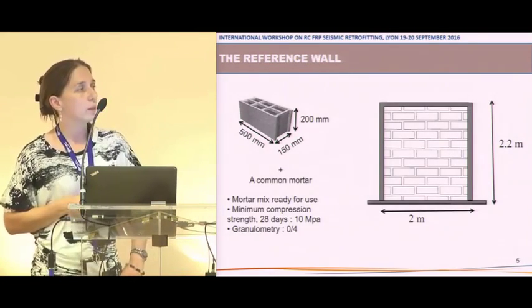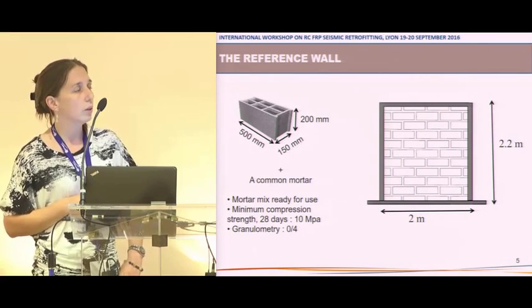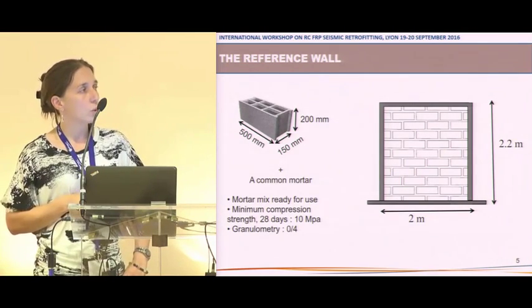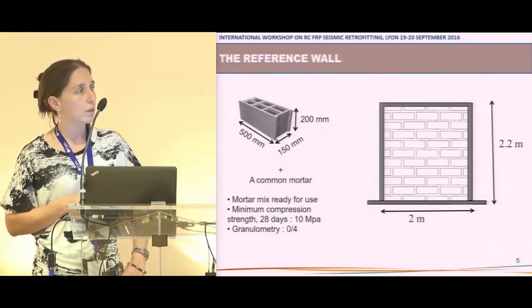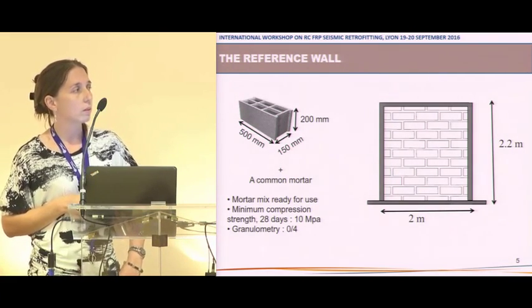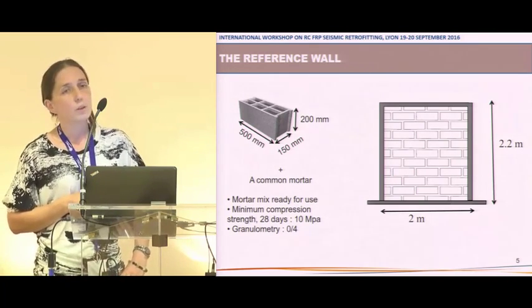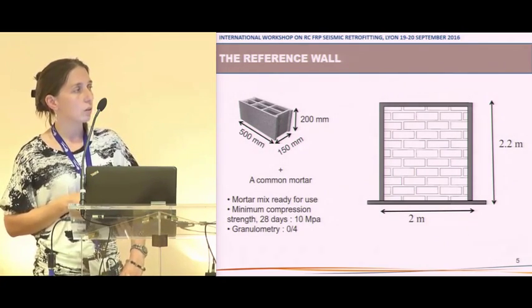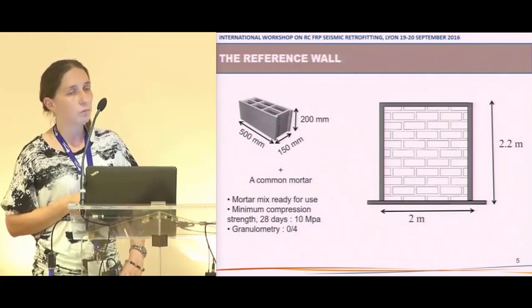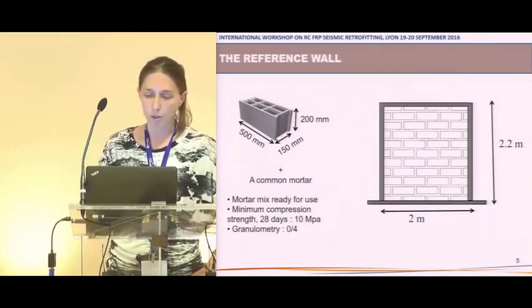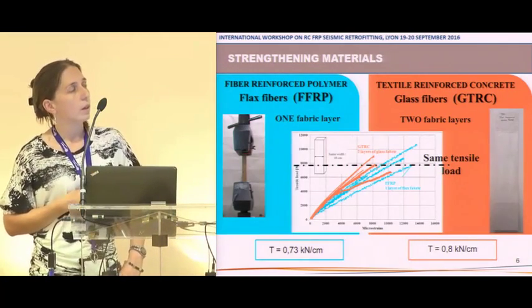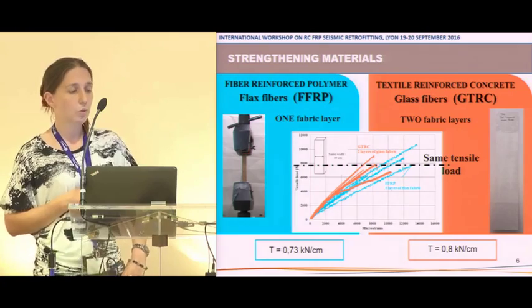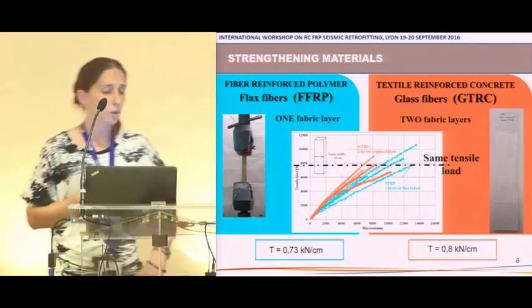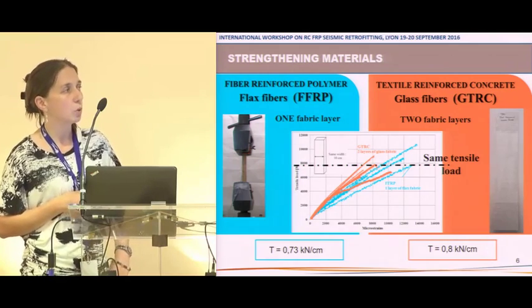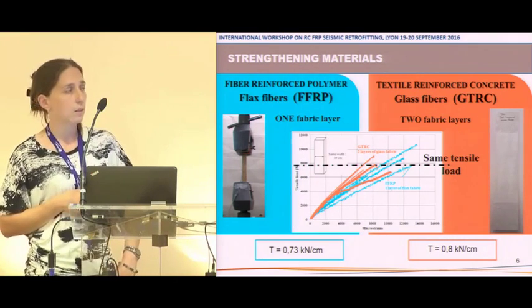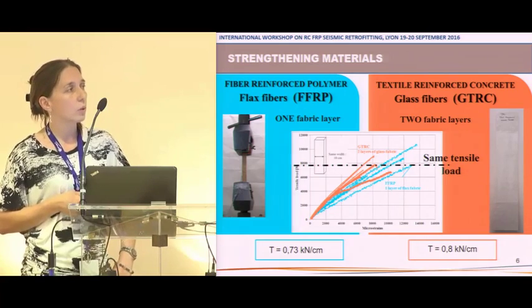All the walls are 2 meters long and 2.2 meters tall, and they are built with hollow concrete block units, whose thickness is around 150 millimeters. They are assembled with a common mortar, which is composed of ready-for-use mix and common cement. Concerning the reinforcement, we have decided to work with two types of reinforcement. The first material is a fiber reinforced polymer with flax fabric, and the second one is a textile reinforced concrete